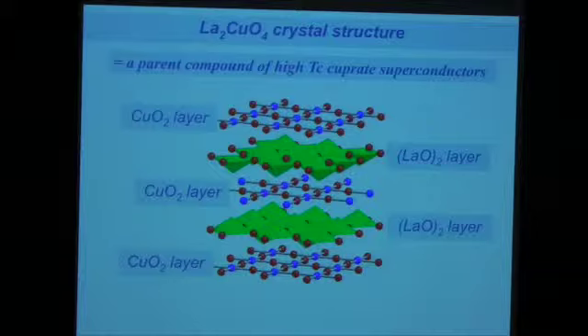Okay, so now let's, for the simple-minded, look at a cuprate, and I'll take lanthanum 2 copper O4 for you, which is basically the fruit fly of the high-TC materials. It's not a superconducting material, but it's a parent compound of the high-TC cuprate superconductors. It has these copper oxide layers, CuO2 layers, separated, in this case, by lanthanum oxide layers that are kind of insulating and where nothing's going on, and then another copper oxide layer where, when doped, the superconductivity emerges.